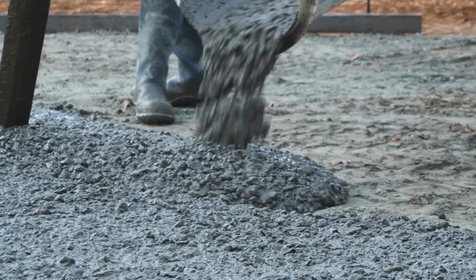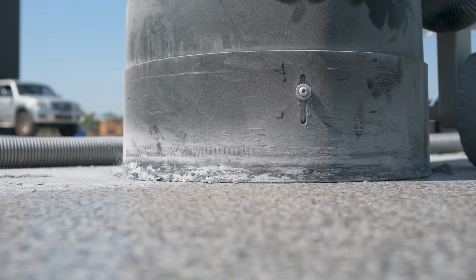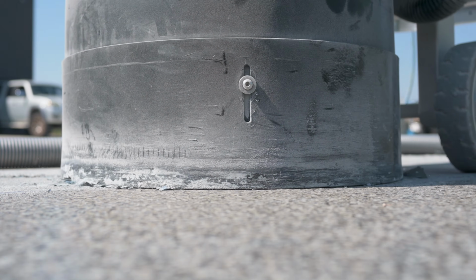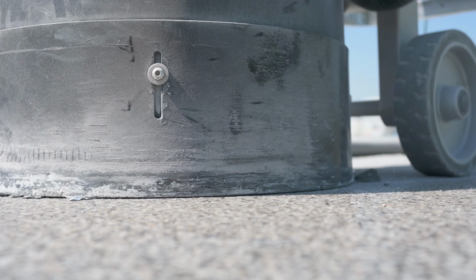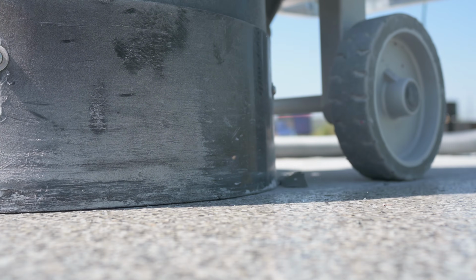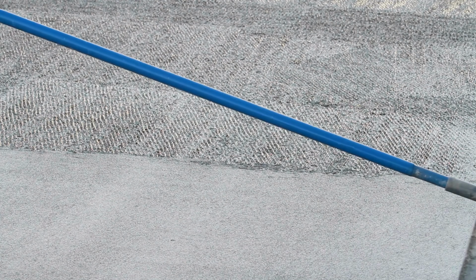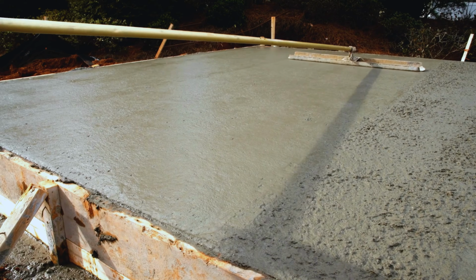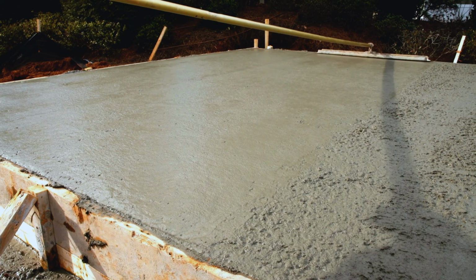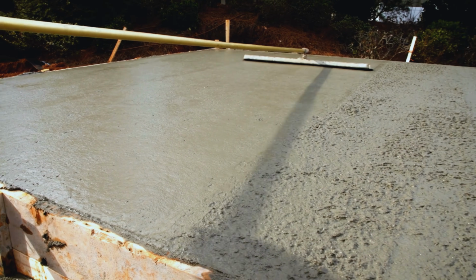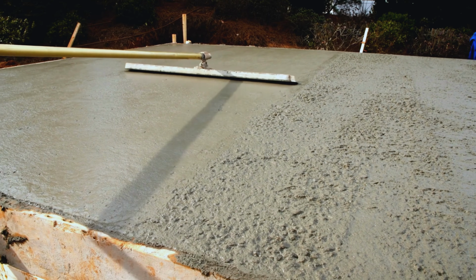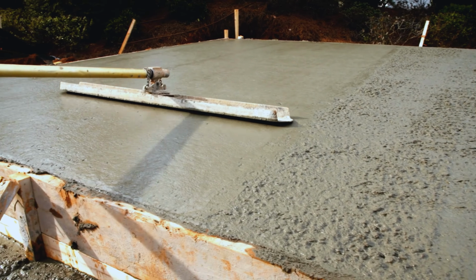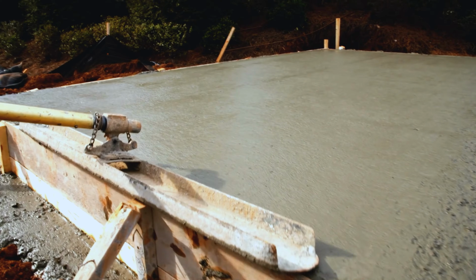They are often below the surface and only exposed once grinding has commenced. Generally, the softer and more porous the slab, the more pinholes you'll find. However, hard and dense concrete is not immune to this issue either. To make matters worse, strength and porosity can vary across a single concrete slab, meaning one end can be softer and more prone to pinholes than the other, most likely where the concrete has been most exposed to heat or over-prepped.